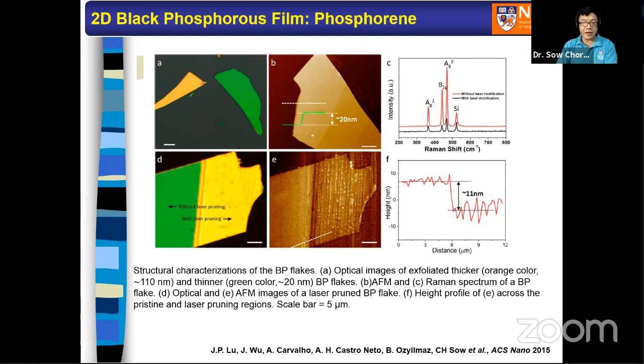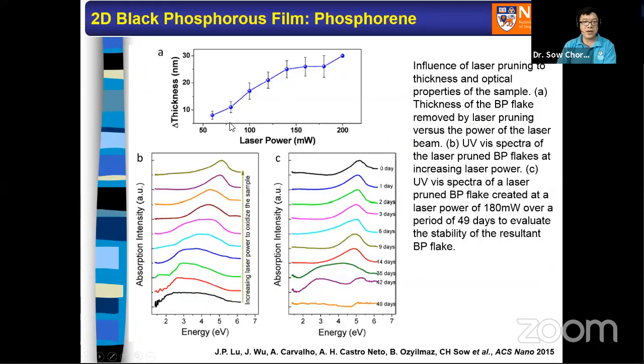And we found that it is quite true. We can use a laser beam with different power to systematically tune the oxidation state of this black phosphorus. And then we find that once the oxidized phosphorus state is achieved, some of the oxidized phosphorus serves as a protective layer and keeps the samples good for more than 2 weeks, 14 days is what we recorded.